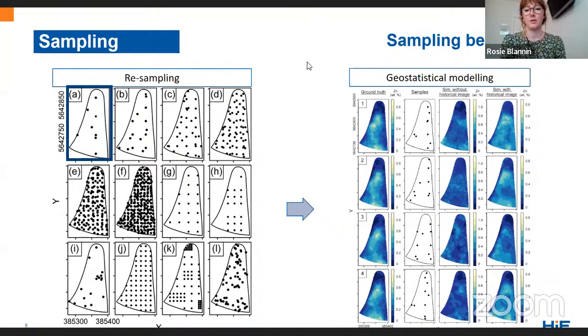So how did we actually do that? Well, we took each of the 1,000 realizations that we had from the previous geostatistical modeling, and we overlaid these sampling schemes. So for instance, this figure on the right shows how we did it with scheme A. And we then sampled the ground truth, so the realization from the geostatistical modeling. And using these new samples, we performed the geostatistical modeling again.